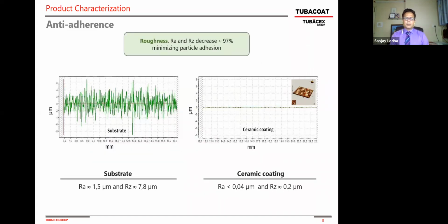So this particular slide is very interesting, it shows the roughness of these coated tubes. What you see on the screen is, on my left, a substrate that's not coated. On my right, the same substrate that's coated. And if you look at the average roughness and the Rz, which is the difference between the highest point and the lowest point, you would see a drop of about 97% from the uncoated tube to a coated tube.